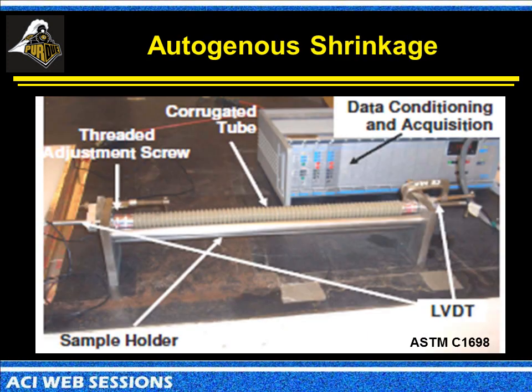One of the issues that we need to be a little bit aware of is autogenous shrinkage. This is shrinkage that occurs without loss of water to the environment. This is shrinkage that occurs without a temperature change, and it starts right when the water and cement come into contact with each other. So the basic idea here is we need to not be using a standard test method like ASTM C157. We need to use a test method that starts earlier, because this shrinkage is taking place in our lower water to cement ratio systems right from the time that the water and the cement come in contact with each other, because it's really driven by the chemical reaction.